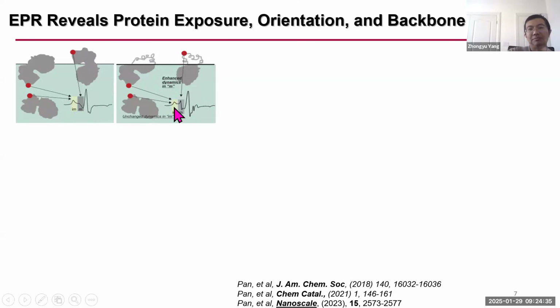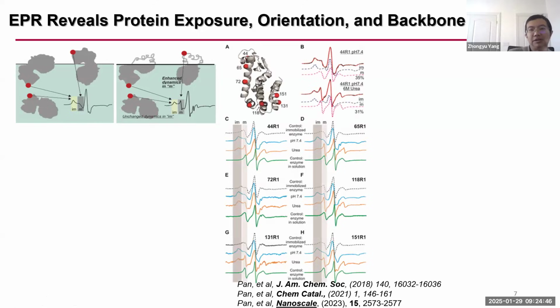And we do the same thing. The immobile peak does not change. The exposed area component gets sharp. That's because of unfolding. And we do the same thing on multiple surface sites of the enzyme. There are a lot of data, the same idea. Find the two components, use urea to unfold the mobile component, and the immobile does not change. We also run simulations to understand the relative contribution, the percentage of these two components. Now, for one site, we have about 33 plus or minus 2% of exposure. That means about 1/3 of the 44 site, which is here, is exposed.